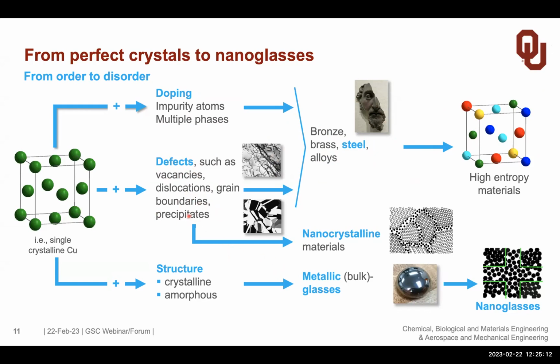If we add grain boundaries to the system, going from a grain size of a micron, which is typical of what we see in an optical microscope, we can make the grains smaller and smaller. For now more than 30 years, people have looked into nanocrystalline materials and their properties and structure. Or we push it further, going from a crystalline structure to the amorphous state, and we form bulk metallic glasses, which you can see here.